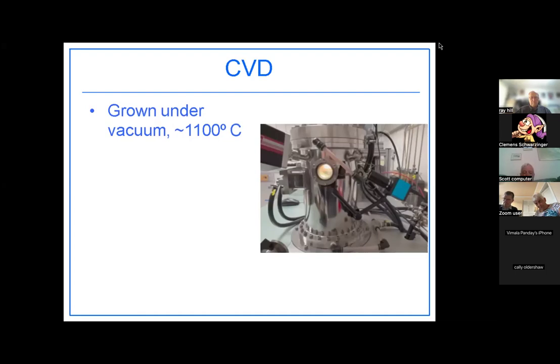And I found this interesting from a chemical aspect in that the reactant gases is 99% hydrogen with 1% methane. And they need the 1% hydrogen to ensure that the diamond vapor doesn't get deposited as graphite instead of diamond. So they heat up this gas mixture. You can see this plasma here, and they heat over the seed, and they heat it using either filament or microwaves, and it just slowly deposits on the surface of the crystal, and it deposits there because it's a little bit cooler than the surrounding environment.